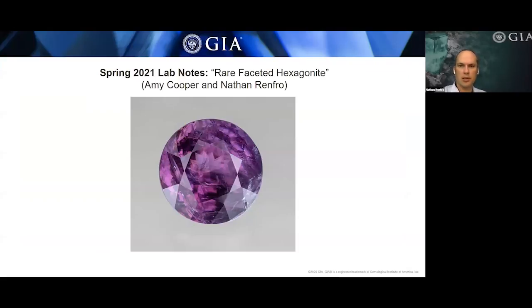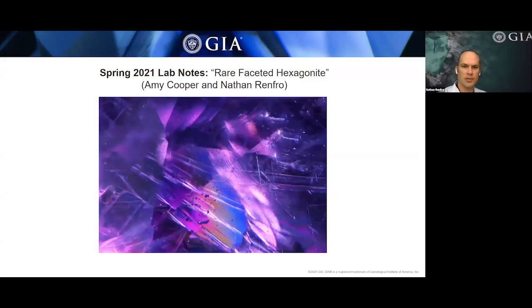We also recently saw in the lab a rather rare faceted Tremolite, the variety Hexagonite. Hexagonite is colored by manganese, and it's this vibrant purplish pink, pinkish purple kind of color. This particular stone was reportedly from the type locality in New York, in the Balmat zinc mines. The stone was faceted by Bill Vance. Tremolite has some very easy cleavage planes, so it's quite hard to cut this material, but you can still see some cleavages in the stone. This stone was a little over 3 carats, so quite large for this material. Really a unique collector stone.